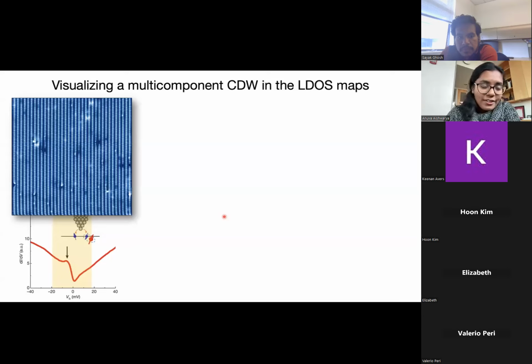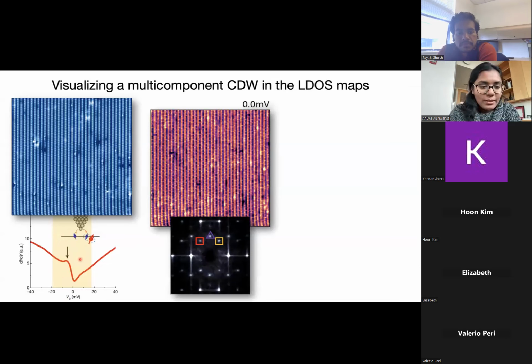So here's a topography, and we obtained density of states maps across different energies in this yellow rectangular region. So this is the Fano peak. We can take a slice at the Fermi energy, which is 0 millivolt, and we can see that the density of states actually oscillates quite a lot. But in Fourier space, we see that it corresponds to the same peaks that we saw in topography.